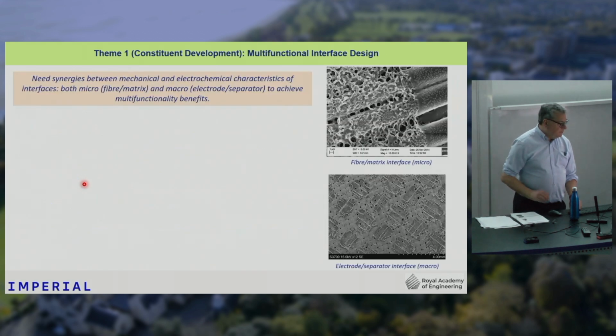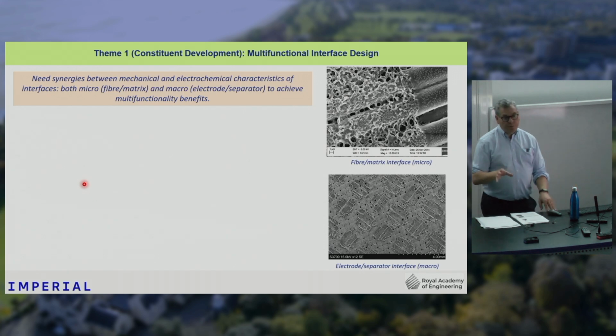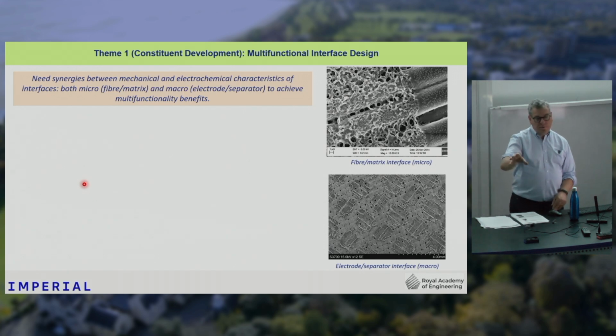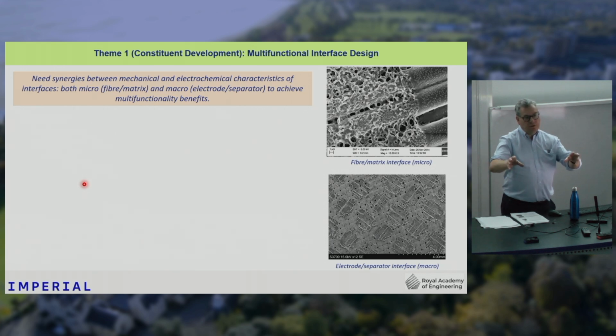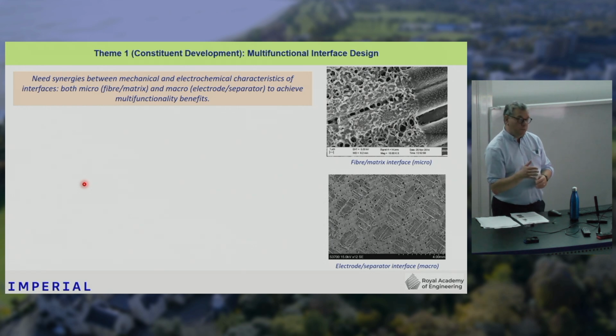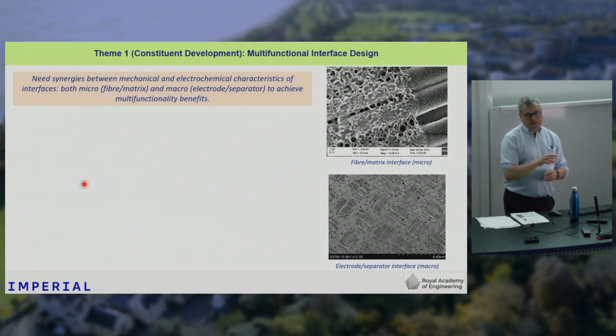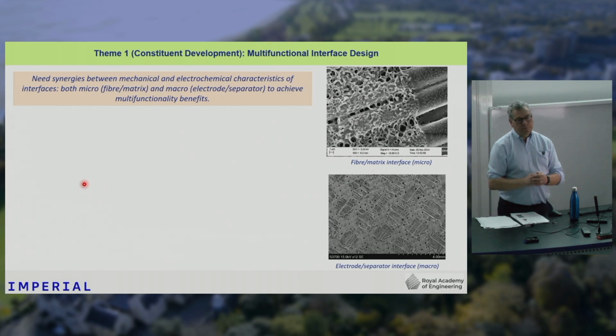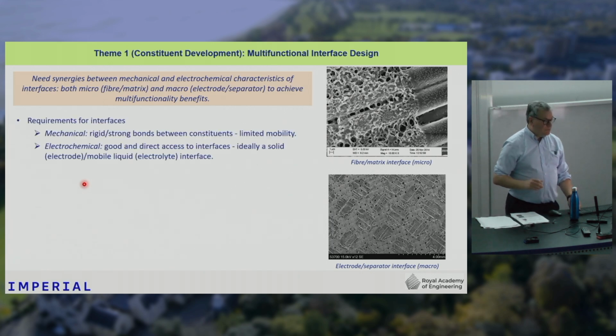And then something that becomes very important: as a composite person, I'm always familiar with fibers and matrices, that's two constituents. You put them together, you introduce a third constituent, which is the interface between the fibers and the matrix. And you find in composites that it's those interfaces that dictate a lot of the mechanical properties. With structural power materials, it's actually the interface that dictates the electrochemical properties as well. So designing the interface is going to be really important. And that's actually at several levels.